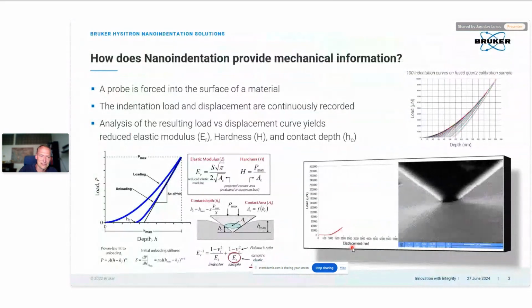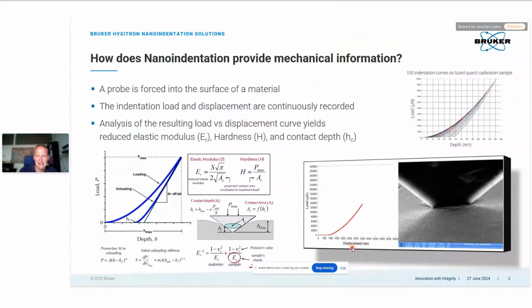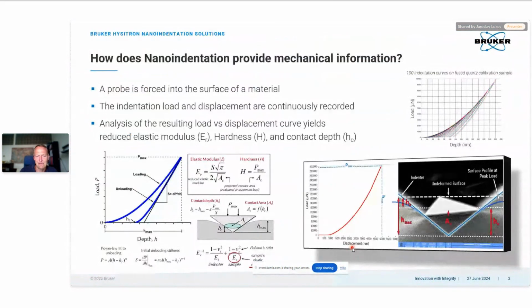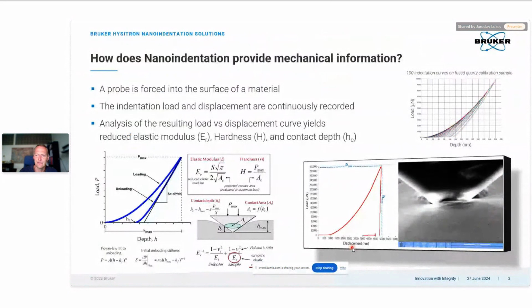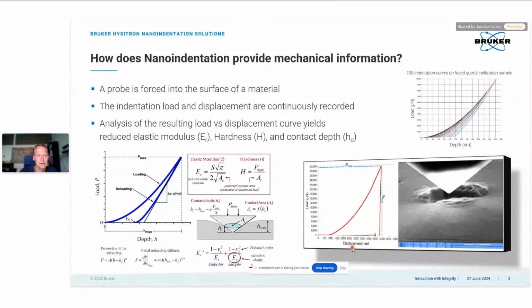So just briefly to remind you what indentation is and what the default values and basic parameters are that we can get, because that's also important for some of the considerations that you need to take into account when you start doing some mapping. So the main output from nanoindentation is the hardness and modulus that we analyze from the unloading segment of the indentation curve, which is a load and displacement curve. The most influential parameter here is the contact area. So the contact area is a real-time contact area at the maximum force.